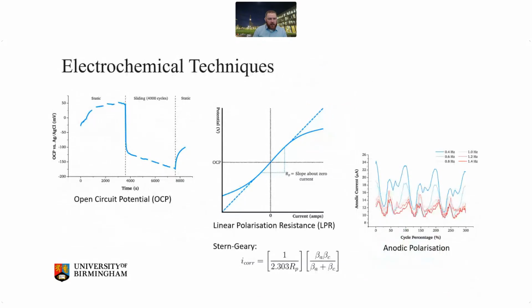So you can use various electrochemical techniques. In particular here, DC electrochemistry, so you can look at the open circuit potential, which gives you a qualitative assessment of what happens to the kinetics of the reactions that are taking place at the bearing surface. You can use the DC techniques like LPR to get a direct measure of corrosion current, or anodic polarization to track the corrosive degradation, that anodic current as a result of sliding and depassivation.